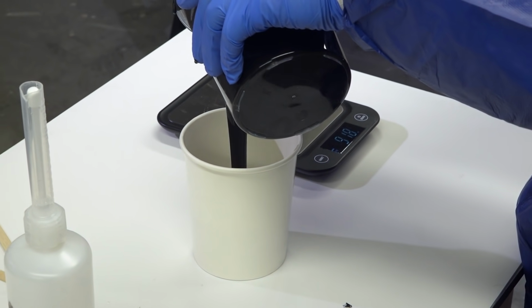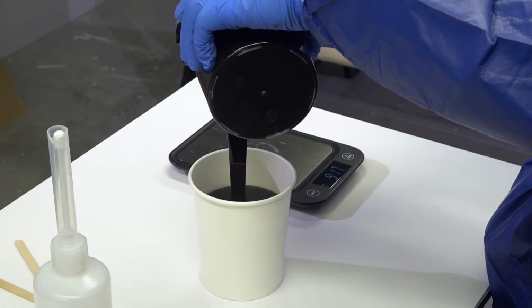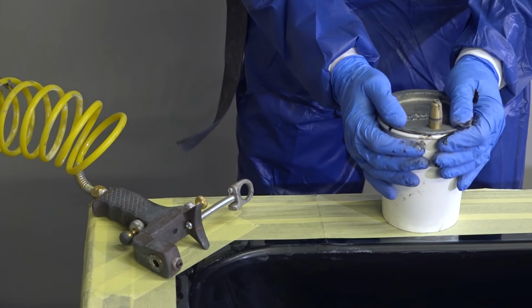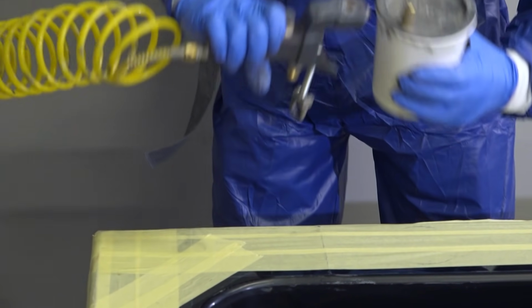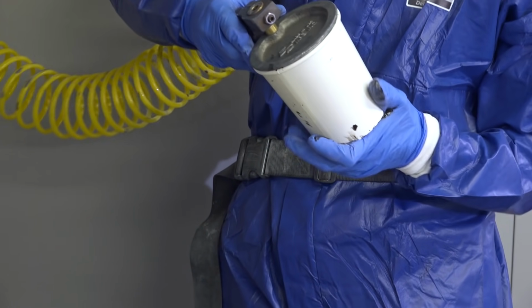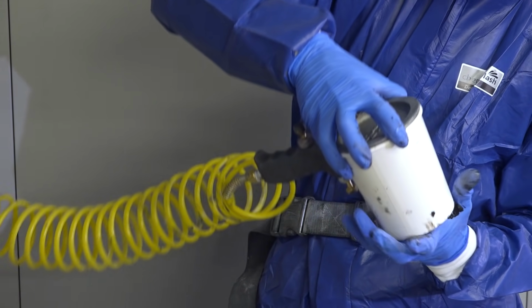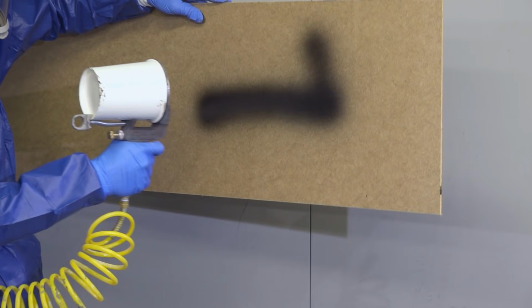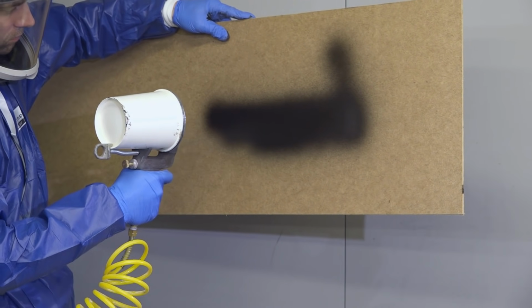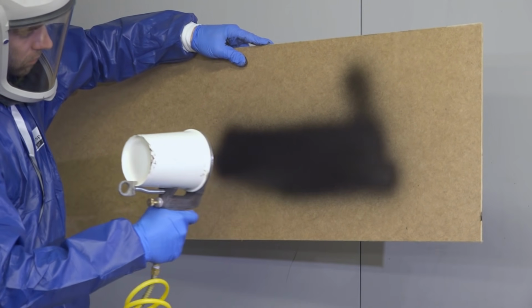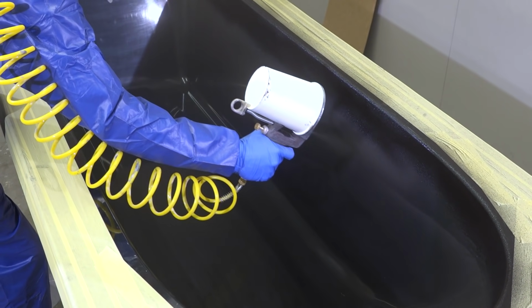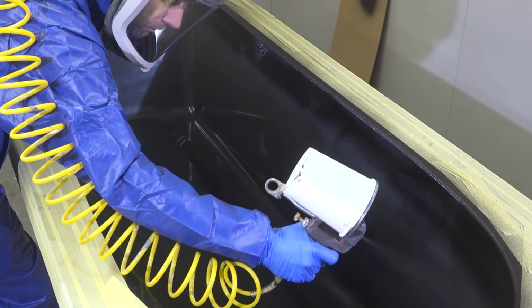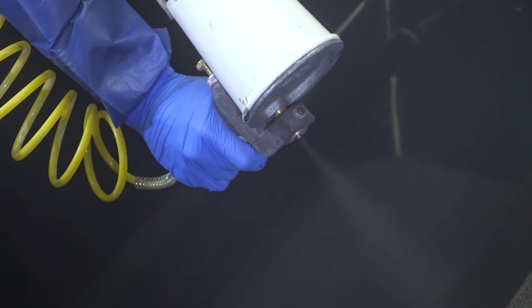With the gel coat catalysed and mixed, it can now be transferred into a paper cup for the cup gun and sprayed. This cup gun is specifically designed for spraying gel coats, which are very high viscosity. They are also very easy to clean, as the paper cup is a disposable element. Although I've chosen to spray the gel, it's most common to brush apply gel coats, especially on smaller parts, and in the case of cosmetic carbon fibre parts, generally no gel coat is used at all, and the reinforcement is infused directly onto the bare mould surface.